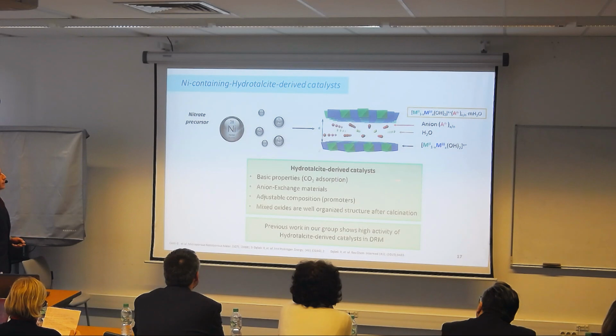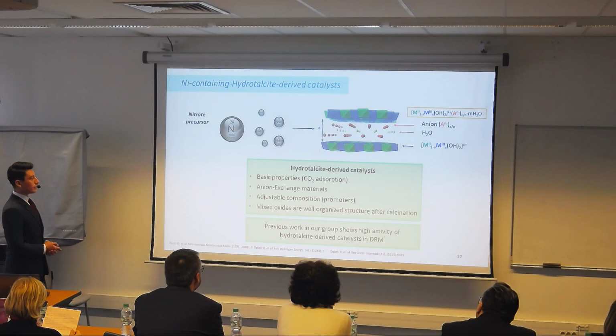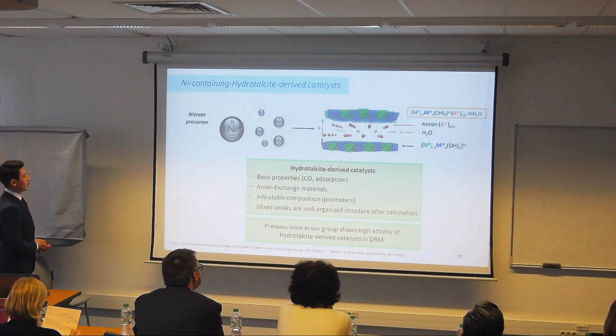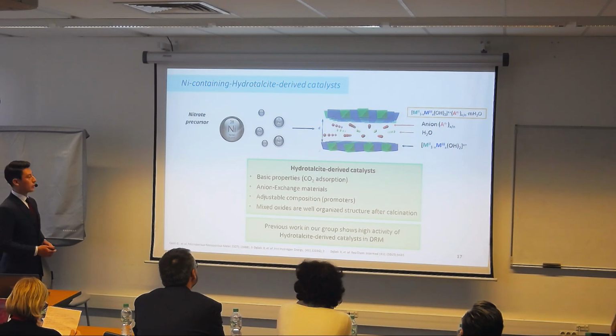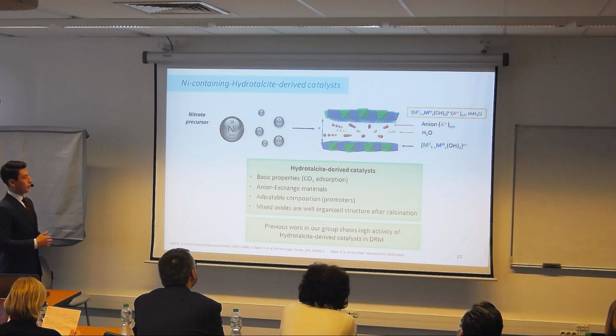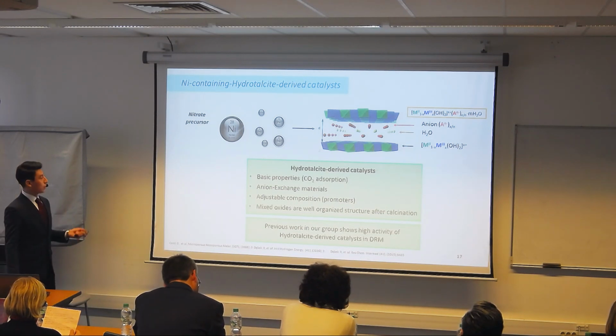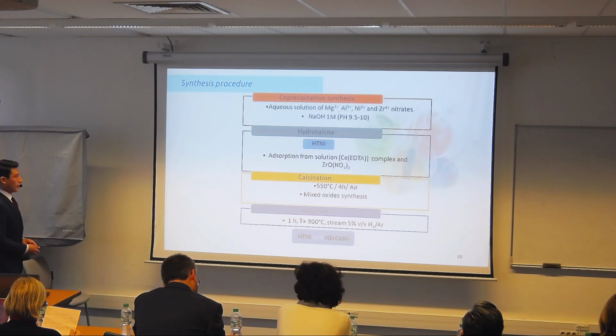These nickel-containing hydrotalcite-derived catalysts were selected because it has been reported that they have basic properties. Also, they have anion exchange capacity. They are very adjustable when we introduce promoters. And after the calcination, they present a very stable and organized structure. Plus, previous work in our group in the laboratory was done, but just for dry reforming of methane, so with equimolar concentration. So we wanted to know what happens when we have excess of methane.